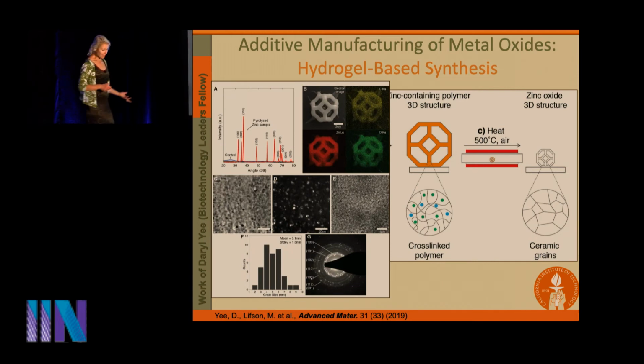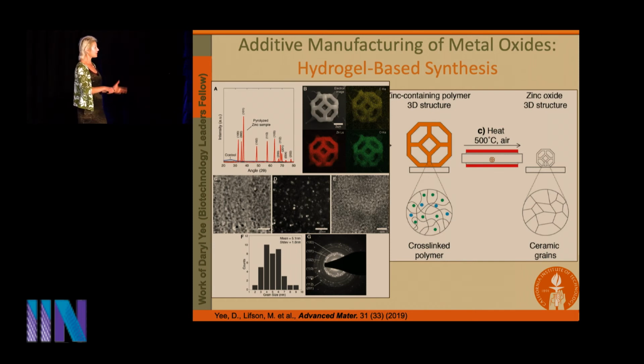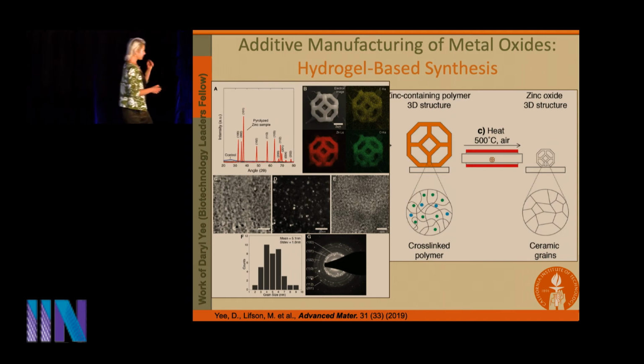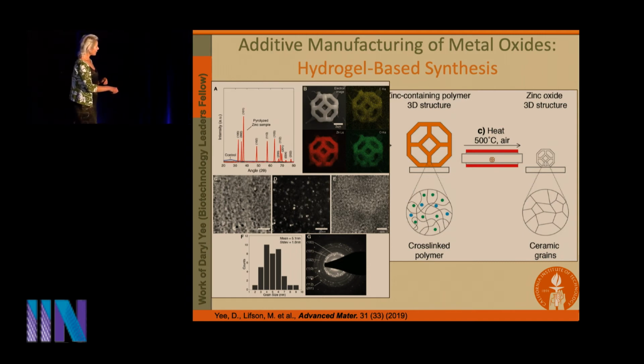So again, trying to understand the nature and the chemical composition of these zinc oxide structures. So it looks like we did in fact make zinc oxide using this hydrogel-based synthesis. This was an entirely new adventure. We didn't know if this was going to work. Sure enough, it did. And what we're learning also here is that it's very nanocrystalline, even more nanocrystalline than the nickel. In fact, the mean grain size here is only 5 nanometers. So what is the one property of zinc oxide that all material scientists know about?